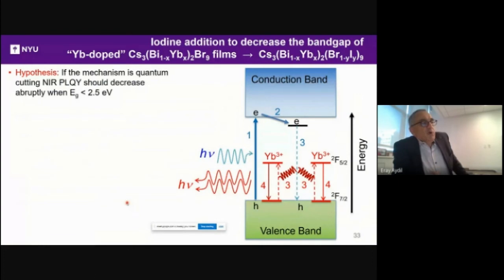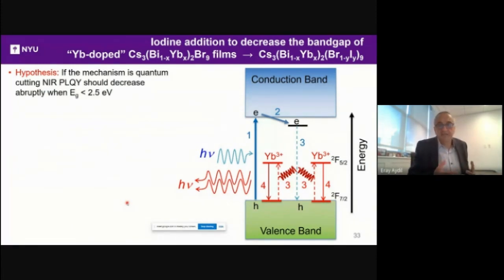So if the mechanism is indeed quantum cutting, the near-infrared photoluminescence quantum yield should decrease abruptly when you decrease the bandgap below twice the ytterbium transition, right? Because you won't have enough energy to excite two ytterbium ions. And 1,000 nanometers is about 1.25 electron volts. So if we decrease the bandgap below 2.5 electron volts, we should stop this mechanism. And one way to do that is by substituting some of the bromine with iodine, okay?